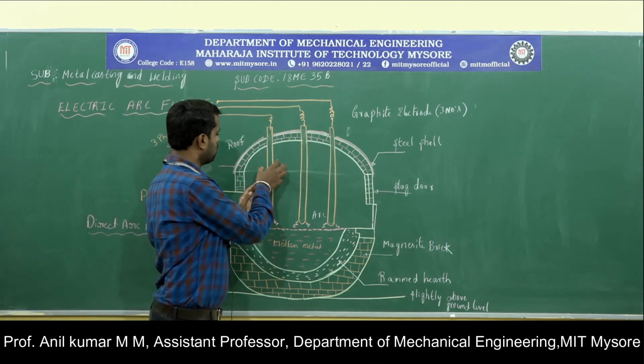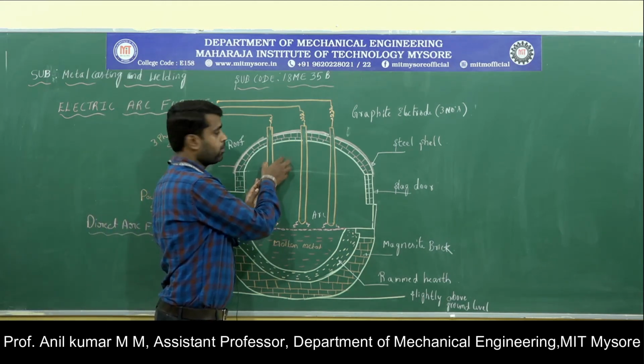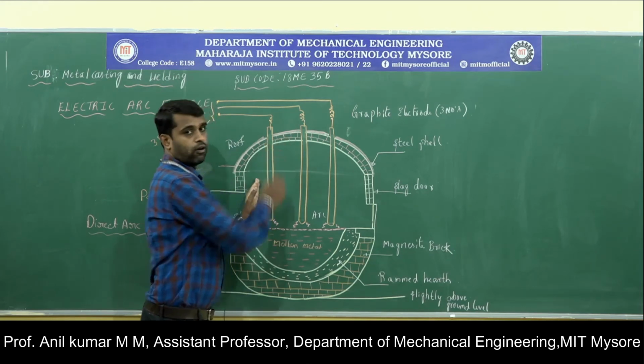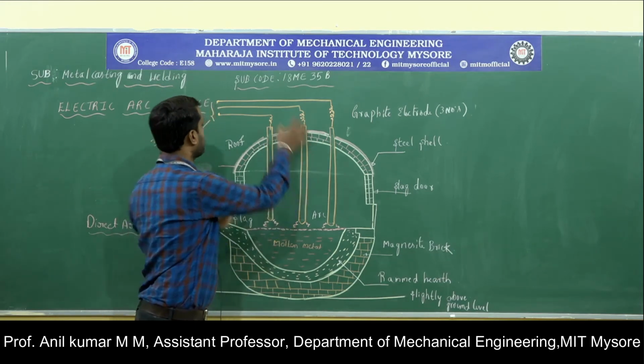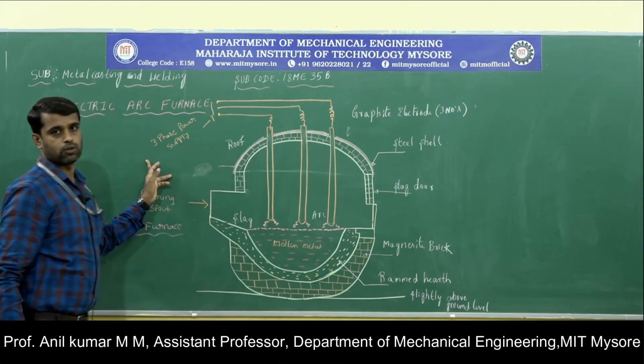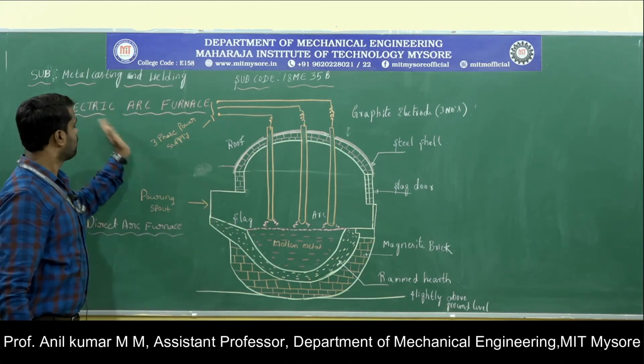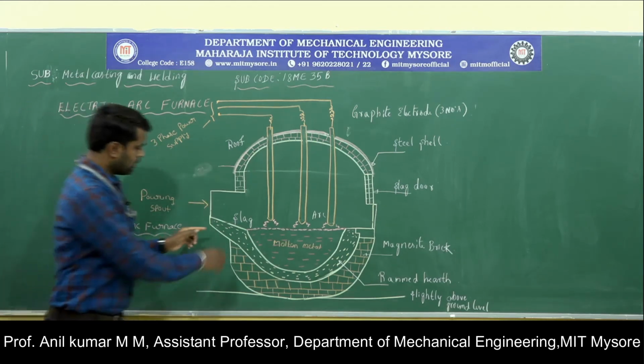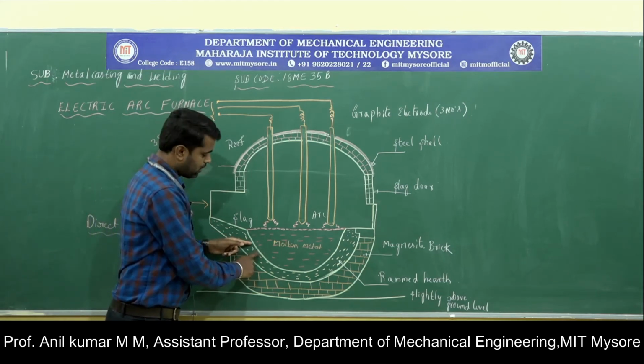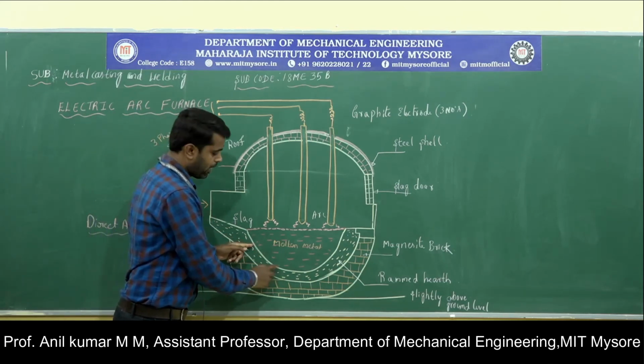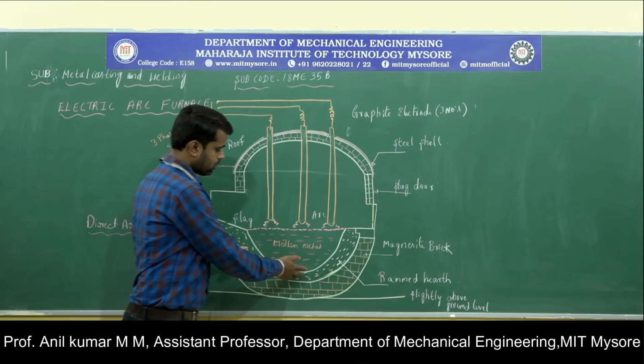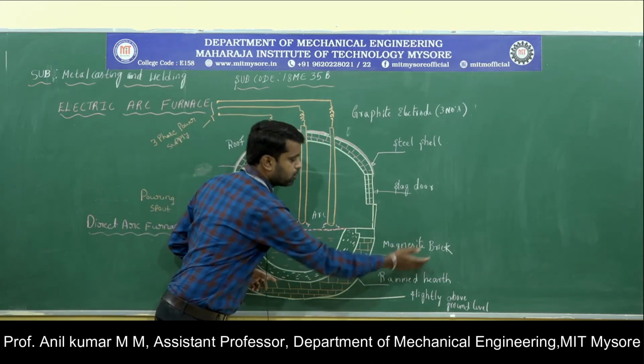Okay, so the non-consumable electrodes will be accommodated through the roof, and these electrodes can be connected to the 3-phase power source. This is the construction part of the direct arc furnace. It consists of the steel shell lined with the refractory material, and the bottom portion of the steel shell is provided with magnesite brick.